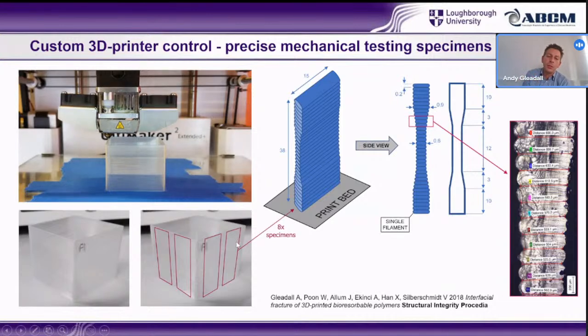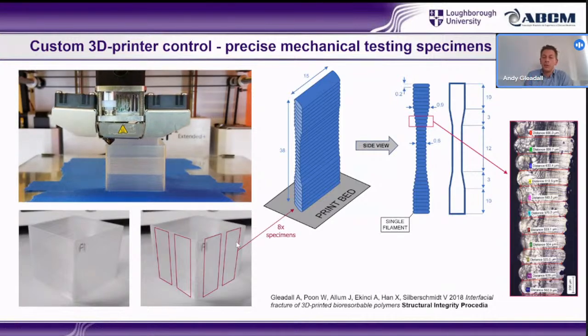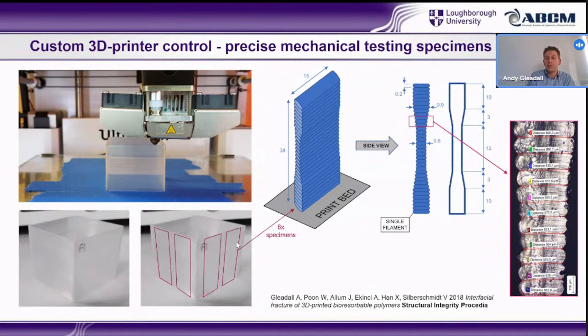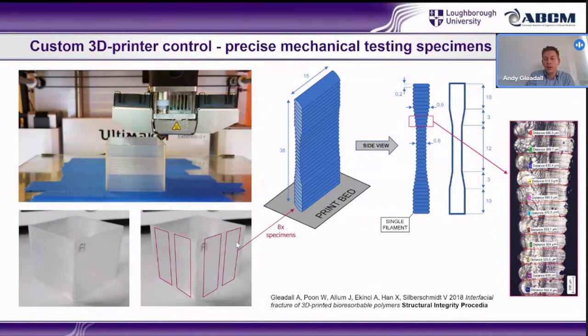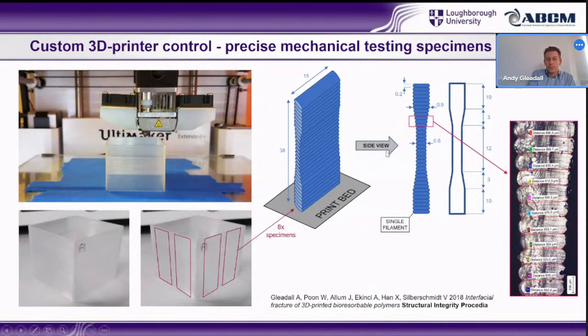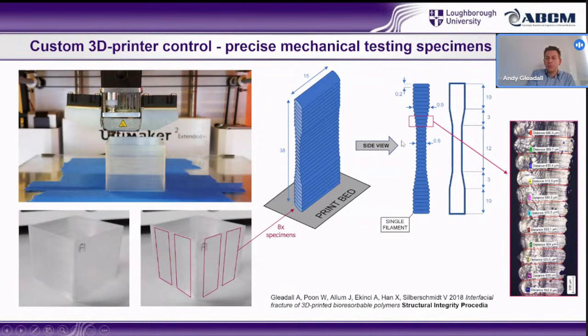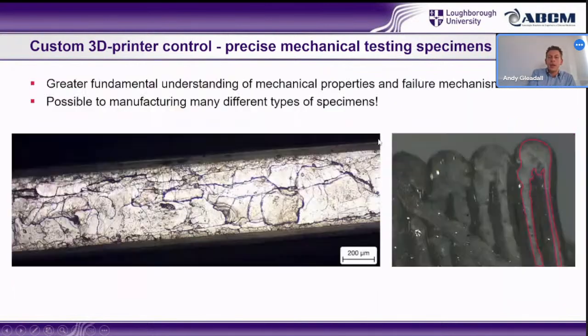When you do have a complicated dog bone die, it's quite difficult to get the actual specimen out of it without damaging it and various other things. And this was a really great specimen for then fracturing it and getting really good understanding of what the interface was like. Here we have a really consistent bond along the length of the filament compared to over here, where it's really dominated by the nozzle changing direction and stuff.